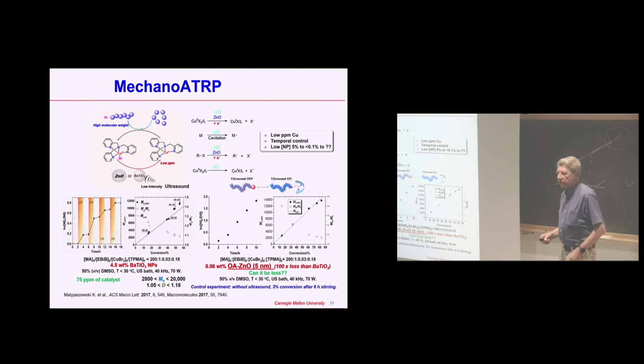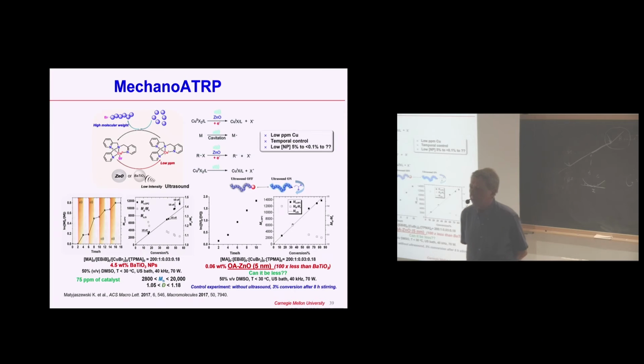Another interesting, sorry. Does the amount of copper you can remove from the reaction depend on the surface area available, or is it independent of that? Yes, you can have a much larger surface area of the electrode, so you can have multiple electrodes as well. Typically we work with a low concentration of copper, 5-10 ppm, so this is really not that much. But you can remove it because it will be electrodeposited. Copper is a conductive material, so you can electrodeposit it very efficiently.